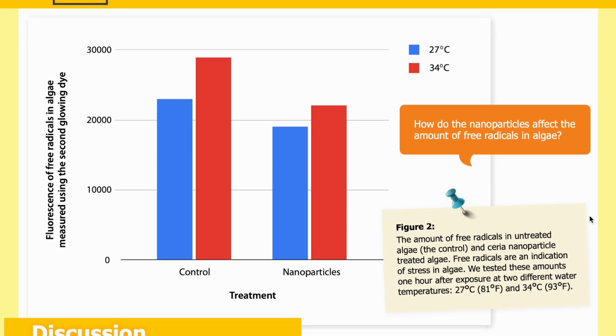Figure 2 shows the amount of free radicals in untreated algae, or the control, and ceria nanoparticle treated algae. Free radicals are an indication of stress in algae. We tested these amounts 1 hour after exposure at 2 different water temperatures, 27 degrees Celsius or 81 degrees Fahrenheit, and at 34 degrees Celsius or 93 degrees Fahrenheit.